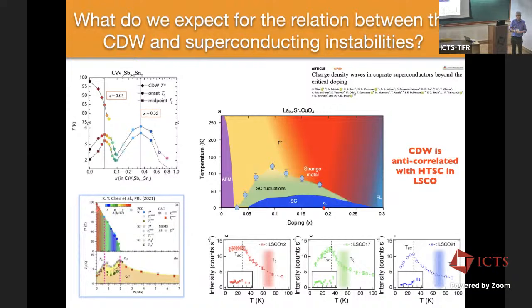Okay, in that case, the superconductivity is definitely established as D-wave superconductivity. And this is not controversial. This has been measured many times over now. And I've taken this from a recent paper from 2021. So this is the Bragg intensity associated with the CDW in LSCO at 3 different dopings. And you can see it's very clear that you get a growth in the order parameter until you get to the superconducting transition. And then for 3 different superconducting transitions, the order parameter either plateaus or decreases by a substantial amount. So it's very clear that the CDW is anti-correlated with D-wave superconductivity in the cuprates.